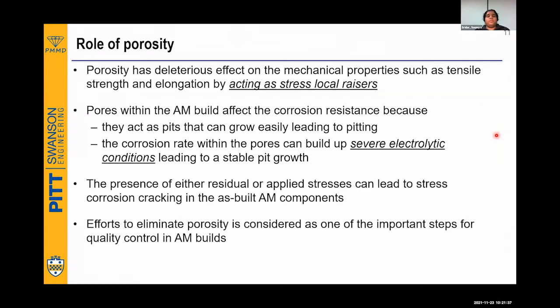So coming to the important thing, the role of porosity. Porosity is always a problem in most of the cases, but in the case of AM parts, mainly two types of properties are going to be affected. First one is the mechanical properties, where it is going to affect the tensile strength and the elongation by acting as local stress raisers. However, the pores will also affect the corrosion resistance, because pores are nothing but pits, which can be viewed as a primer for pitting corrosion.